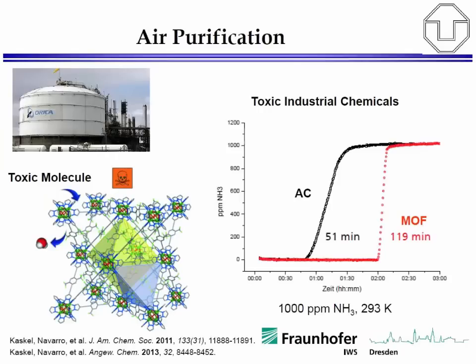And this is shown also in the next slide, where you can see an example for TIC removal. TICs are toxic industrial chemicals. A typical example is ammonia, which is still used in chemical industry to a wide extent, or also even in cooling applications. It's quite common for ice cooling engines, and also for heat pump machines, basically. Therefore, it's a certain hazard. And here we show that the MOF significantly outperforms activated carbons. This is also a breakthrough curve with almost 2 hours holding time for the breakthrough, and a very steep curve as compared to the activated carbon, and showing that this is also very effective for the toxic gas removal from air applications.